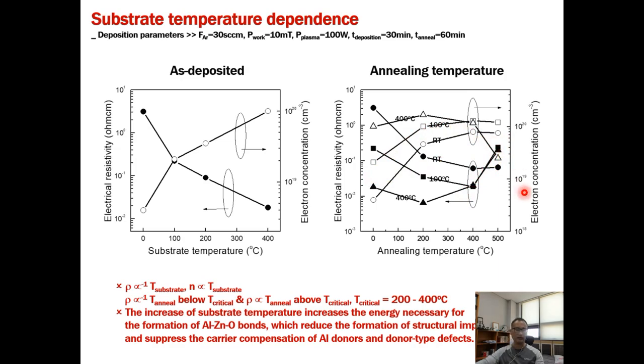We can say that the increase of substrate temperature increases the energy necessary for the formation of an aluminum zinc oxide bond, which reduces the formation of structural imperfection and suppresses the carrier compensation of aluminum donor or donor-type defect.